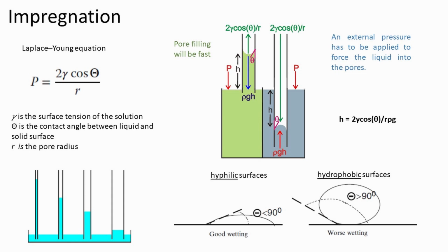First, we consider whether or not the solution will enter the pores of the support, which is a matter of wetting. For hydrophilic materials, pore filling will be fast. However, if the support is hydrophobic, then the capillary pressure is negative and an external pressure has to be applied to force the liquid into the pores. A typical example of a hydrophobic support is carbon.